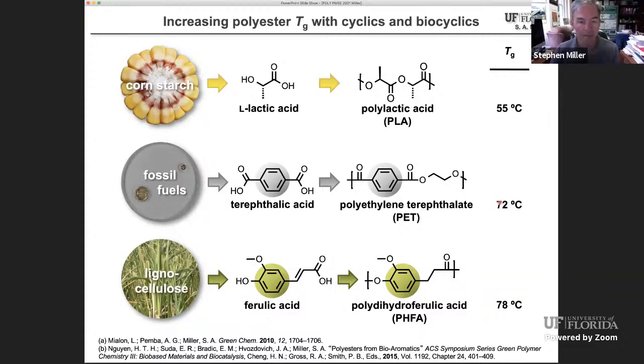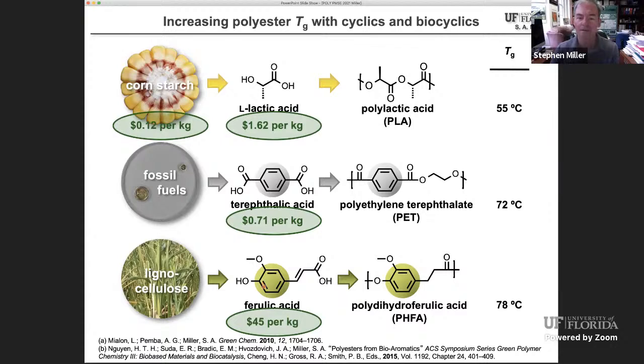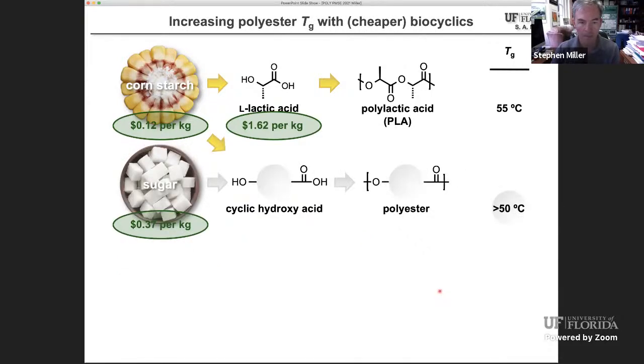And when you make this polydihydroferulic acid, or PHFA, you get a Tg that looks a lot like that of PET itself. One of the problems is that even after bargaining on Alibaba.com, you're still paying about $45 per kilogram for ferulic acid. So it's not all that cheap. And if you buy these vitamin supplements, it's about an order of magnitude more expensive than that to buy it in the tablet form. So that's never going to compete in the commercial realm for making something that is so simple as to just hold water. So what we want to do is take the design strategy and essentially have a ring. So we believe that rings, and I think it's well appreciated that rings in polymer chains limit conformational freedom and therefore tend to boost glass transition temperatures.